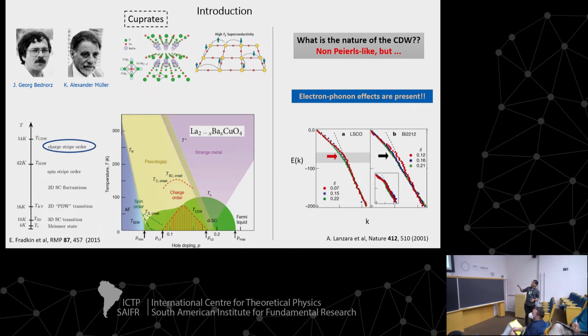If you look here, for instance, this is a very well-known result from 20 years ago that shows by ARPES measurements the dispersion of the electrons in cuprates. And we see that we have a kink here, and this kink is exactly at the phonon energy of the in-plane oxygens. So probably this kink here comes from the coupling with the phonons of the plane. So there is indeed coupling between the electrons and phonons in cuprates, although we believe that the phases are driven by electron-electron interactions.